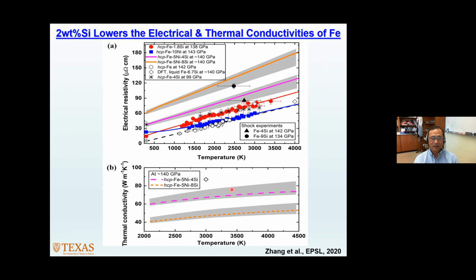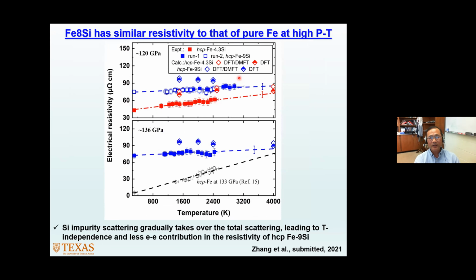Okay, and so if you use the Wiedemann-Franz law, then the thermal conductivity is expected to decrease. So for an iron-silicon alloy system, we can expect the electrical and thermal conductivity to be additive. So you can actually use the data set here from pure iron to 2% silicon and extrapolate to high pressure, high temperature conditions. Okay, so that's what people generally believe. But when we conducted experiments on iron with 8% silicon, our results are actually quite different.